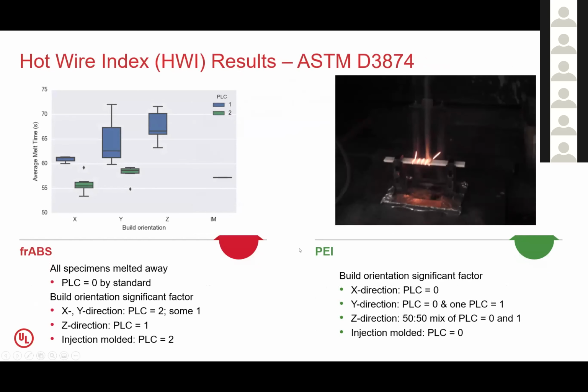If I look at hot wire index or a glow wire index as being a similar type of test, where we're applying an energized nichrome wire to our specimen and looking for the time to ignition, we are again starting to see results. All of our ABS samples, probably not too surprising, melt and drip away from the nichrome wire. So it would, by definition of the standard, get the best result. However, if we consider the length of time it took to melt and drip away, we are now starting to differentiate based on build orientation as being the most significant factor. Whether it was printed in the horizontal plane or in the vertical plane had the greatest impact.